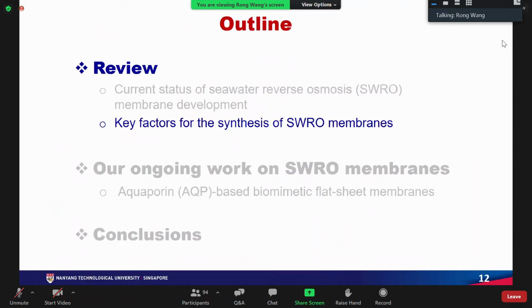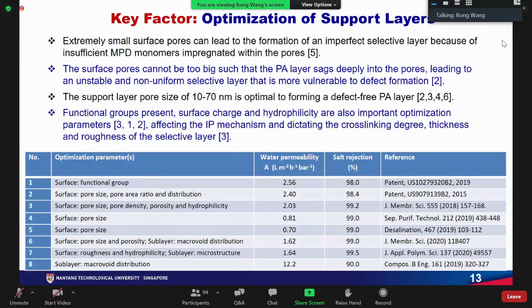So, what can we learn from the literature? Here, I summarize some key factors and challenges for the synthesis of the SWRO membrane. I will go through this information in the following slides. Some research concerns the substrate. Indeed, the substrate is the platform for the interfacial polymerization to form the selective layer, so the surface property and pore structure will definitely affect the IP layer formation. So people try to optimize the support layer in terms of the pore size distribution and the pore density. Also, people try to adjust the surface charge and the hydrophilicity of the support layer in order to get better membranes after applying the interfacial polymerization. Some key references in recent years are listed in this table.